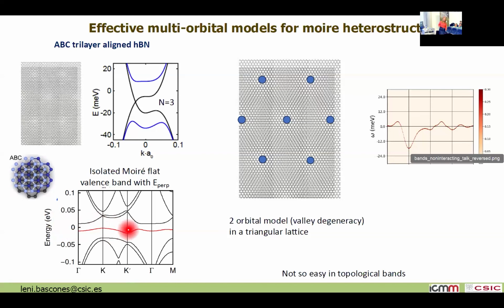Okay, so in this case, it's interesting. One of the bands is trivial in the topological sense, so it's similar to what one would have in just a single orbital model on a normal lattice. The other one is topological. If we just look at the band that is trivial, we have a valley degeneracy, so we have two bands. So one can really model this system in terms of just a triangular lattice in which we have this very big atom at the center of our unit cell. This is also the idea that I mentioned before. And you get, well, this is plotted in different directions, but you get these bands, and you can work with this to make your models, or your understanding. Okay.